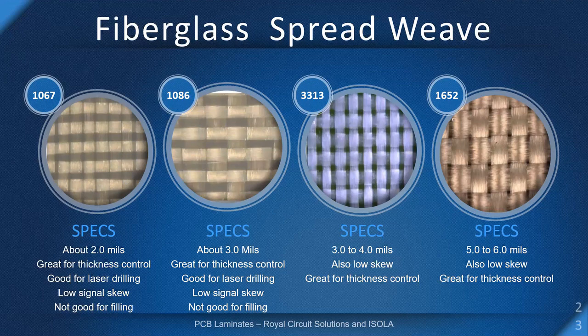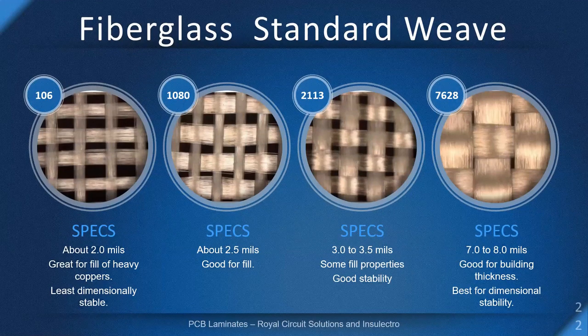Relatively new are the spread glass prepregs. They are primarily there for signal performance purposes. We talked a little bit about skew earlier. I'm going to talk more about that. Really what it does is it provides a uniform micro Dk effect. So if you remember the previous slide, in fact, I'll go back. If you look at the 1080 and 106, you see open areas. Imagine if you would a trace going over the open areas versus a trace that's going over one of the glass bundles. You could see that they would have different dielectric field effects around that trace, which would change its propagation velocity of the signal and could cause skew on differential pairs.